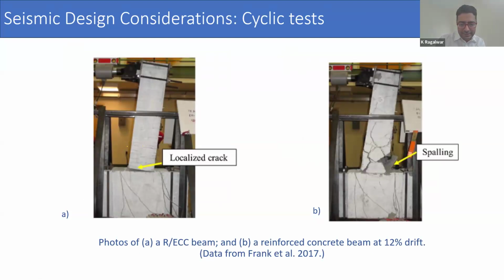So now if we focus on the hysteretic behavior, in conventional concrete, hysteresis loops often pinch inwards as the load reverses. This pinching effect reflects low stiffness during the tension-compression transition. It happens because the wide cracks lead to bond deterioration and reinforcement slip. So there is erosion of the bond. So the structure loses stiffness and energy dissipation capacity. Reinforced UHPC or FRCC, HPFRCC by contrast, show much less pinching. That's because the bond between the reinforcement and the matrix is preserved by these fine distributed cracks and the fiber bridging. As a result, HPFRCC beams can dissipate significantly more energy during a cyclic load event.